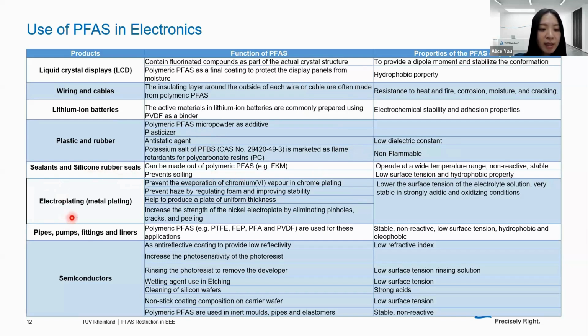For electroplating, PFAS can prevent the evaporation of chromium-6 vapor in chrome plating and also prevent haze by regulating foams and improving stability, because PFAS can lower the surface tension of the electrolyte solution. Also, for some pipes, pumps, fittings, and liners, polymeric PFAS, for example, PTFE, FEP, PFA, and PVDF are used for this application.